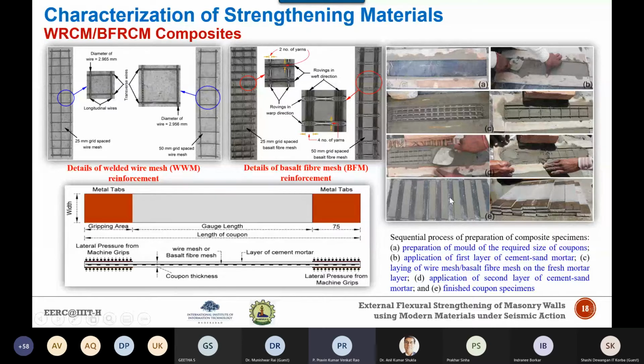And the reason for providing the metal tabs, as I already mentioned, is to avoid damage to the specimen when you test it in the universal tensile testing machine, because the hydraulic grips in the test machine may damage the specimen. Therefore these metal tabs are very important to provide the shear stress transfer, in order to improve the stress transfer mechanism at the mortar reinforcement interface.